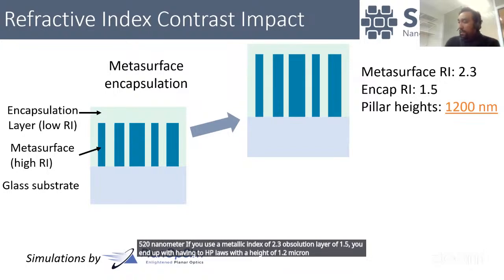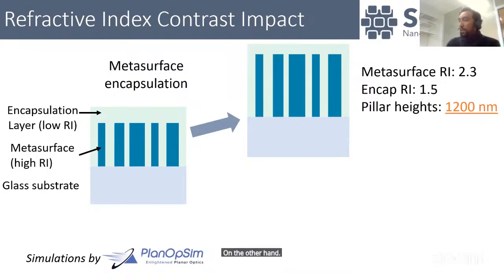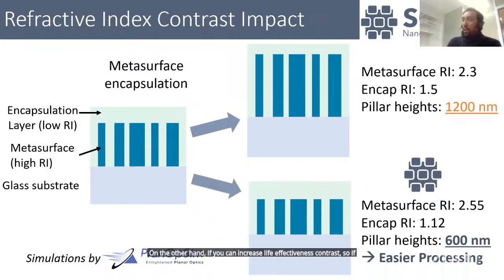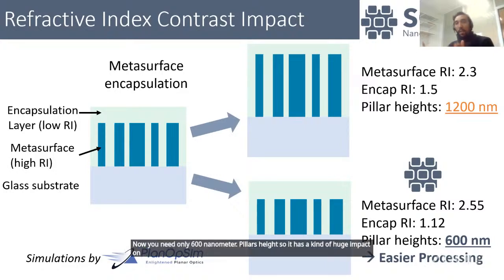On the other hand, if you can increase the refractive index contrast, so if you can go to a refractive index of 2.5 for the metasurface, and reduce the refractive index of the encapsulation to 1.12, now you need only 600 nanometer pillar height. So it has a huge impact on the processing. Using this wide range of refractive index allows you to simplify your process.